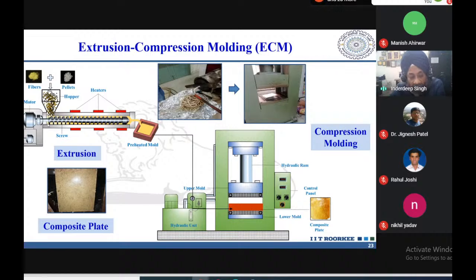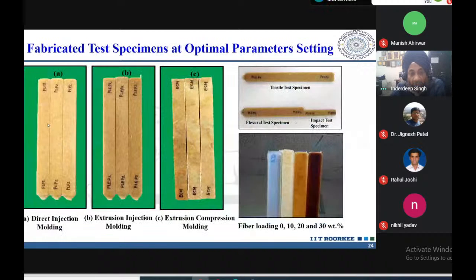So if we use continuous fibers in the form of different layers, maybe 4 layers or 6 layers or 8 layers, in that case we will call it a composite laminate, because there we have laminated different layers of fibers with polymer. Now these are the fabricated test specimens at optimal parameter setting. So you can see direct injection molding samples, extrusion injection molding samples, and extrusion compression molding samples also.